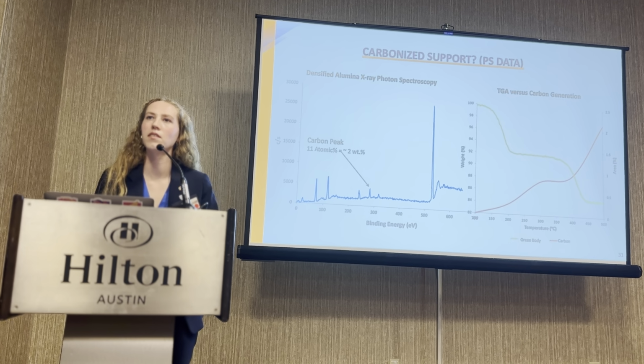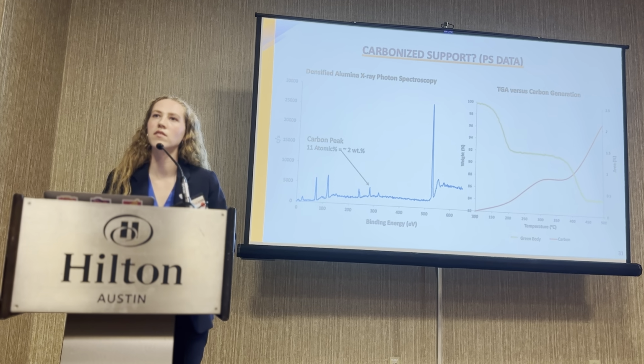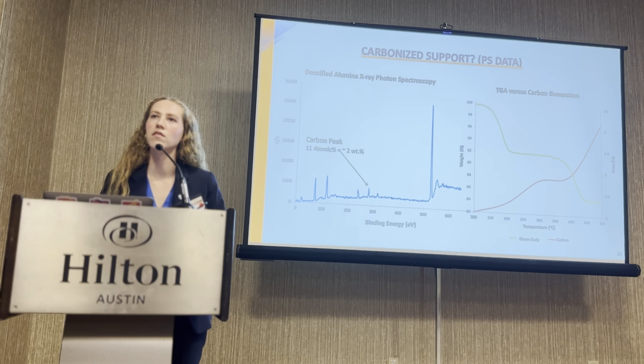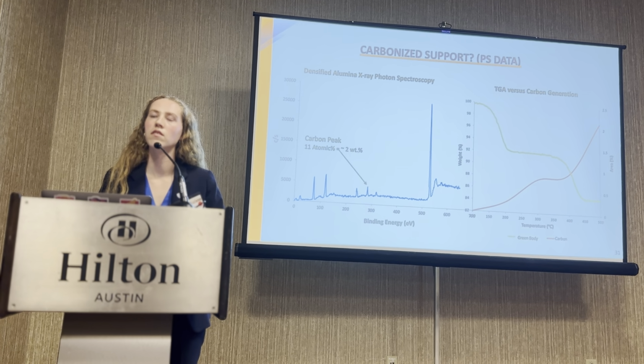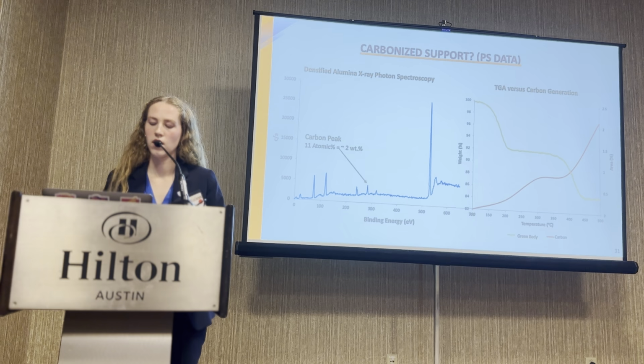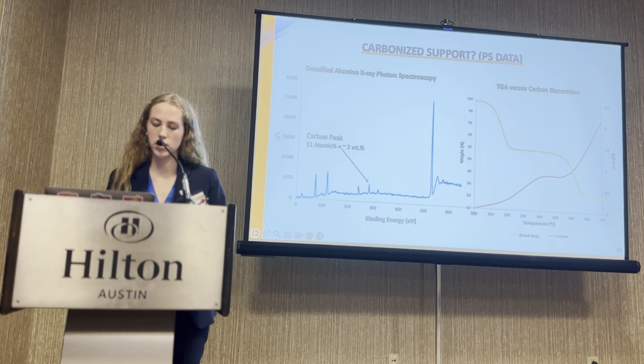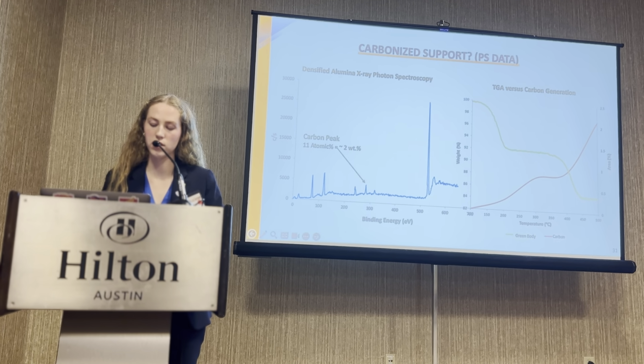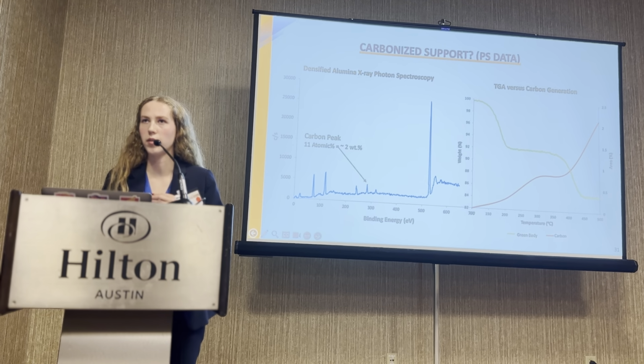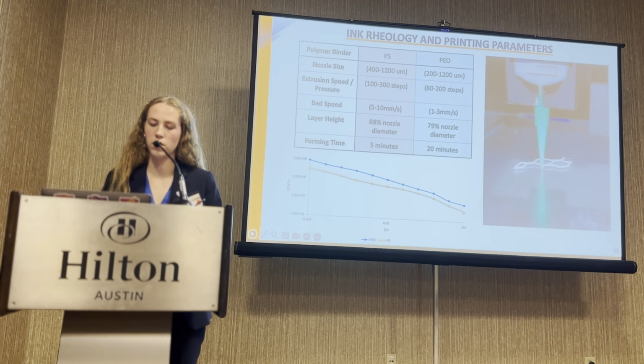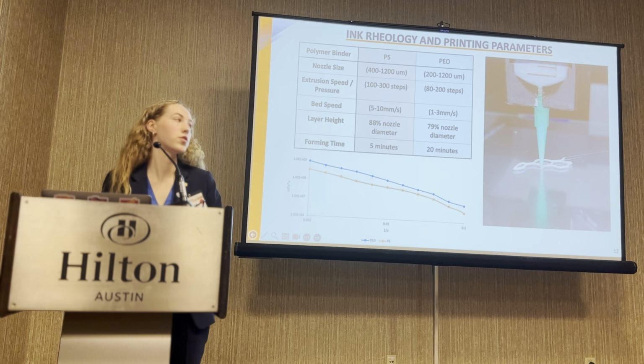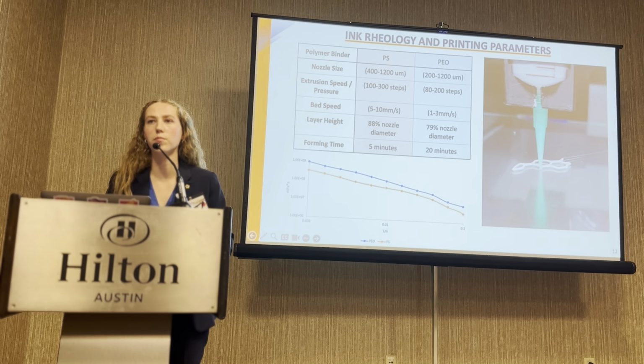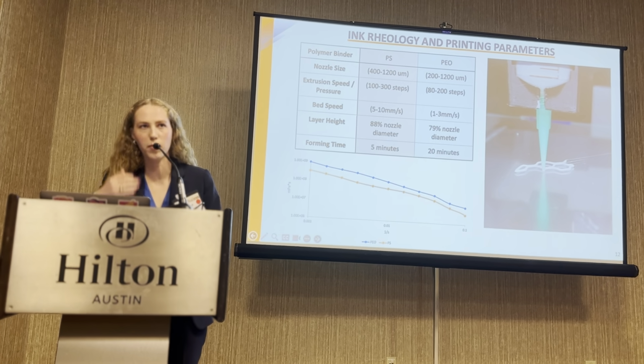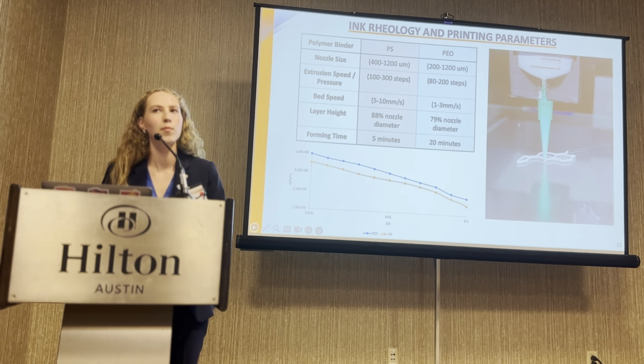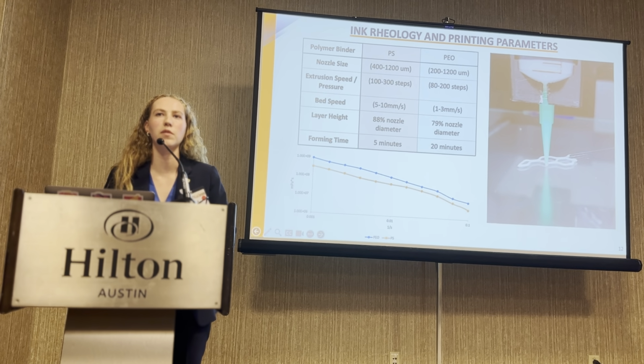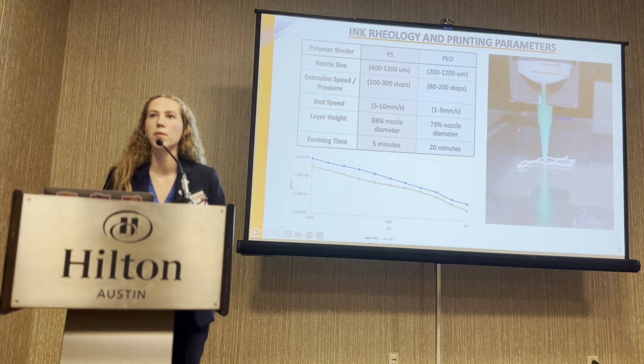There was a slide where you highlighted the relative setting time. How long does it take to set? For the polystyrene, about 5 minutes to set before it cracks if you try to bend it. For the PEO, about 20 minutes, as you can see. But to your comment about the moisture content in the room, we've seen some of the polystyrene prints be flexible even a day after.